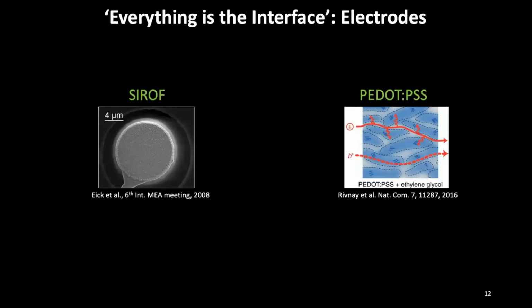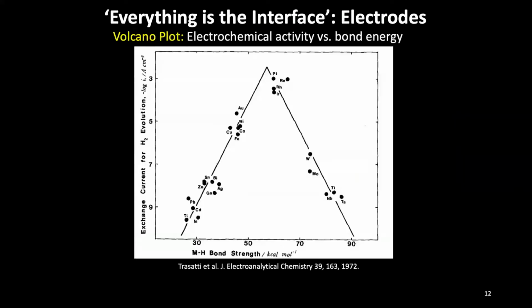And this has been applied in sputtered iridium oxide films, or even in PEDOT, which has a volumetric sensing mechanism, because it's a one-dimensional polymer, so ions can penetrate in between these one-dimensional long polymer chains and then interact with the polymer layers. But if we want to design an electrode that has the highest sensitivity, we need to look at what's called a volcano plot from electrochemistry.